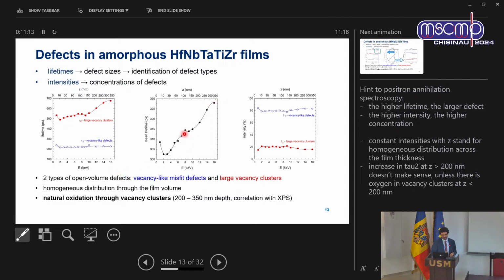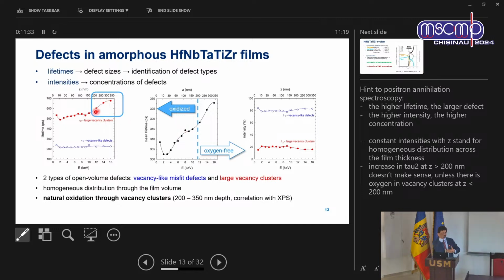So if we correlate these depths with oxidation, what's happening is that the film has uniformly distributed defects, and this size increase in the vacancy clusters is actually a transition from an empty vacancy cluster to clusters which has inner surface covered with these oxides. So this is the mechanism of oxidation of amorphous films, and the responsible defect are vacancy clusters. So if we want to make more oxidation-resistant films, we need to get rid of those vacancy clusters. This is the next step forward.